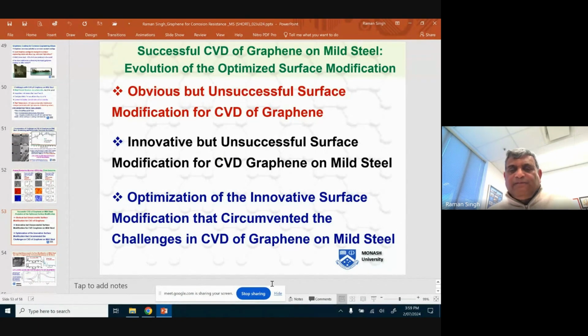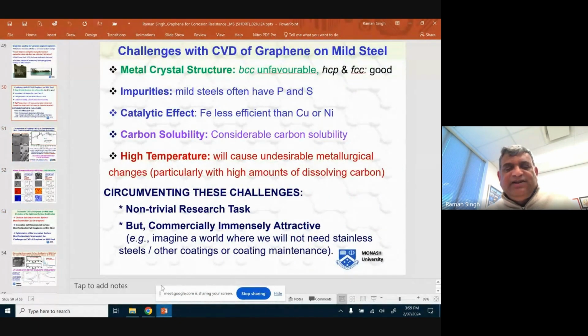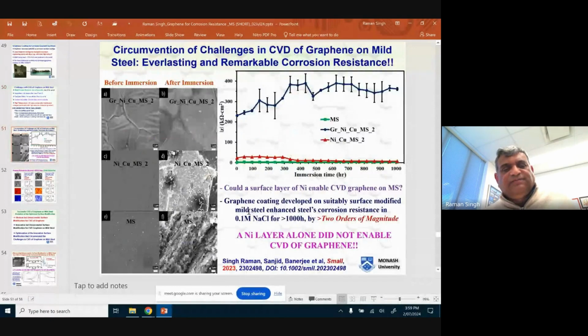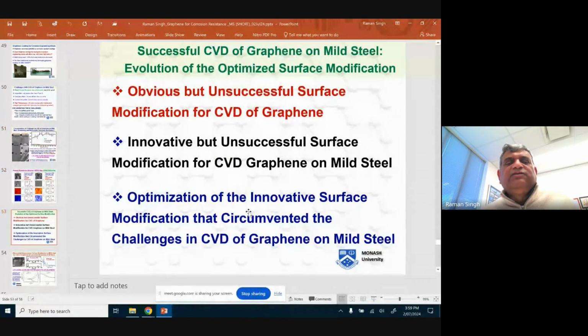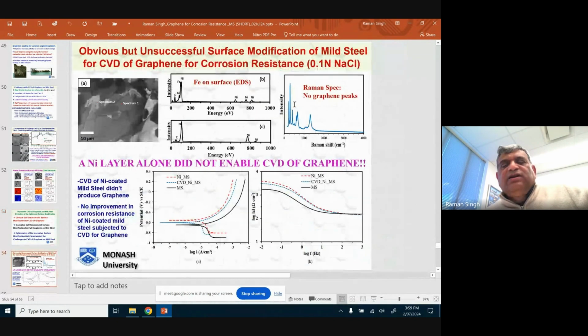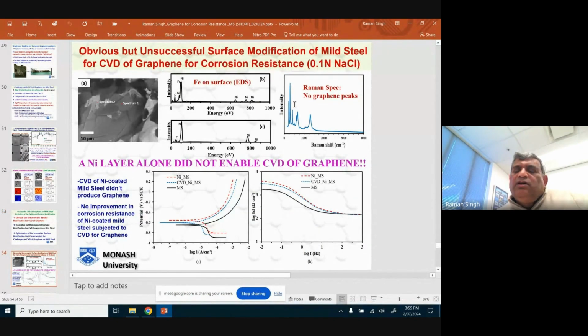We said in an earlier slide, it is a non-trivial research task. How did we achieve this? We undertook some obvious surface modification before trying to develop graphene. That did not work, and I will tell you what that obvious surface modification is. We had success in developing graphene on nickel. Why don't we develop a very thin layer of nickel on top of mild steel, and then try to develop graphene on nickel? It does not work.